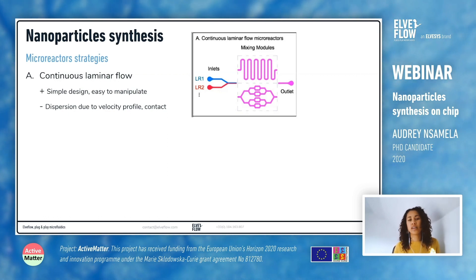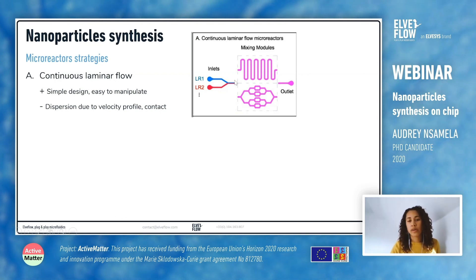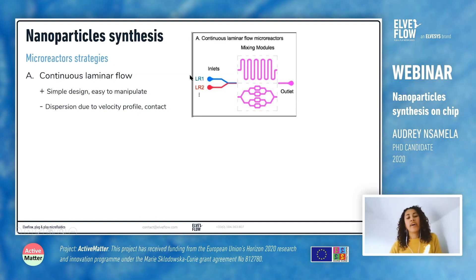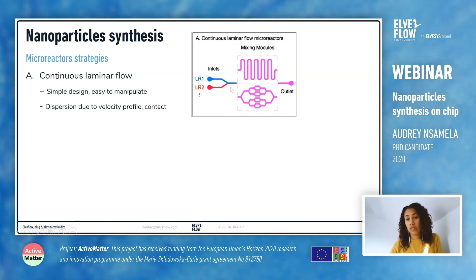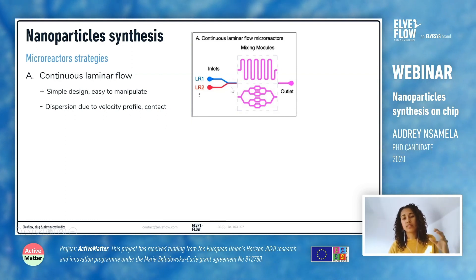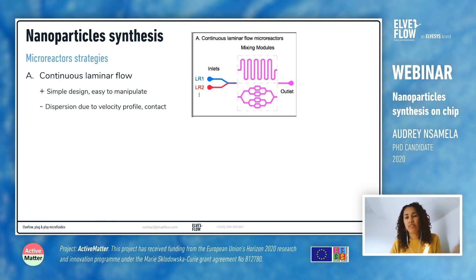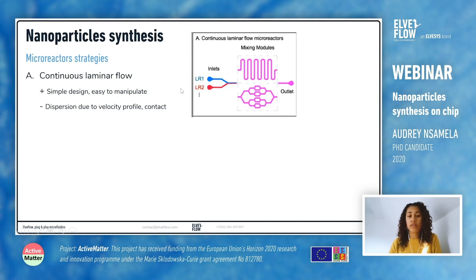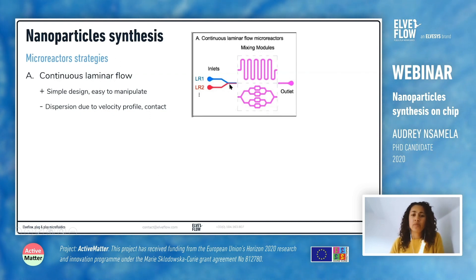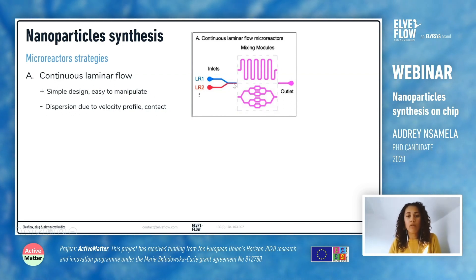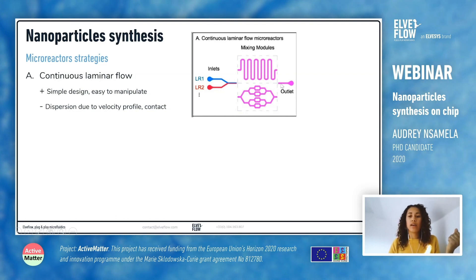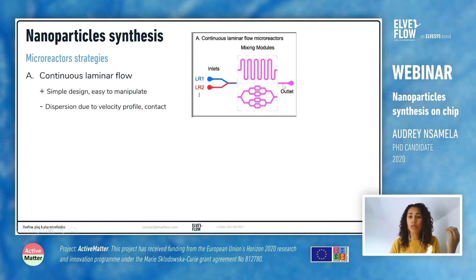With continuous laminar flow microreactors, you basically have reagents flowing alongside with mixing modules to ensure your reaction proceeds well. The drawback is that you have dispersion in your fluid due to the velocity profile — in microchannels, velocities have a parabolic profile, which can lead to dispersion and affect the quality of your nanoparticles. You also have the problem that your reagents and product are in contact with the channel walls, which is a problem especially if you're using solvents incompatible with the material, or if your nanoparticles can diffuse into the material, especially with PDMS. Furthermore, the nanoparticles can stick on the walls, leading to clogging.